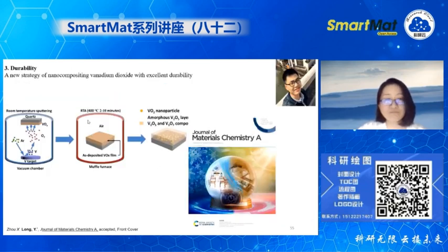This one is a collaboration with Zhou Xin. He's from Sichuan, I think it's Chengdu Dianzi Daxue, I can't remember exactly. He was my exchange student, a visiting student who came to my lab for 1 year. He did fantastic work. They came up with a way: room temperature sputtering first, followed by very rapid thermal annealing. They obtained a structure with vanadium dioxide nanoparticles embedded in a V2O5 and V3O7 matrix, and on top a very thin layer of V2O5.